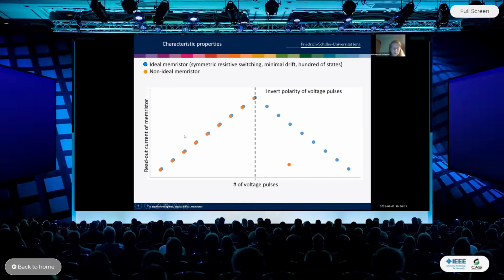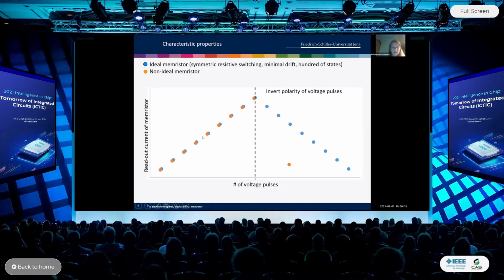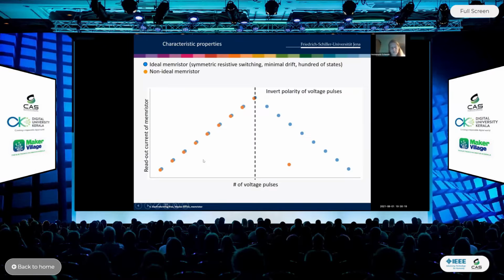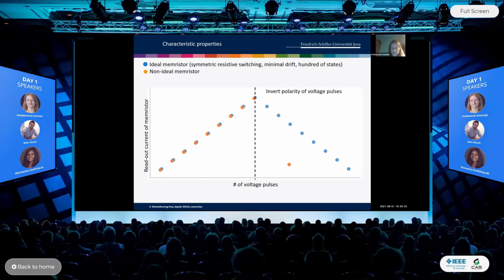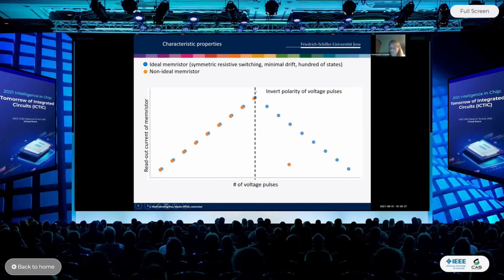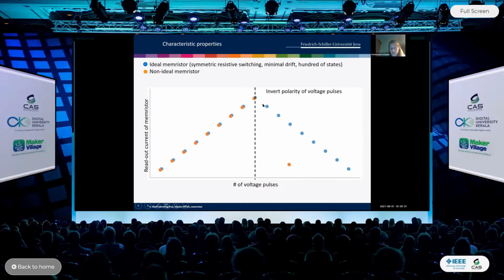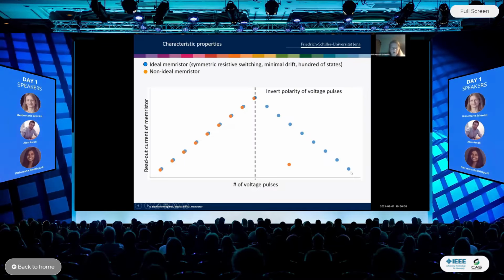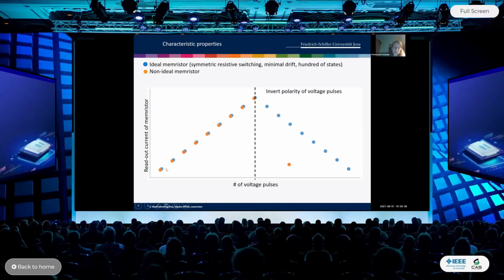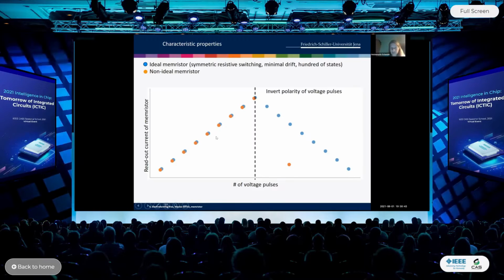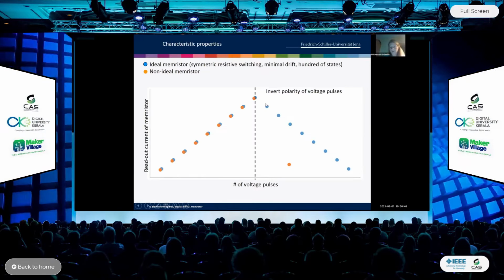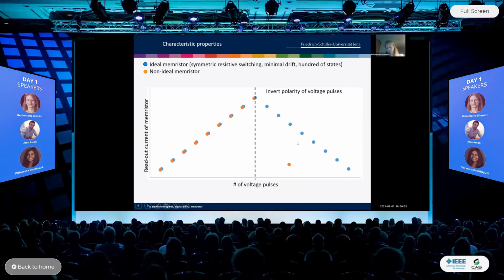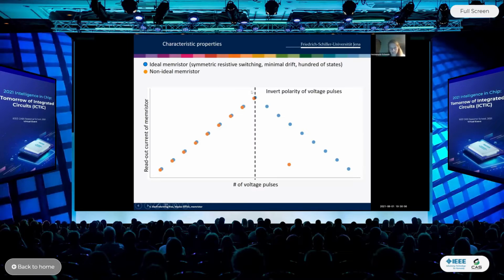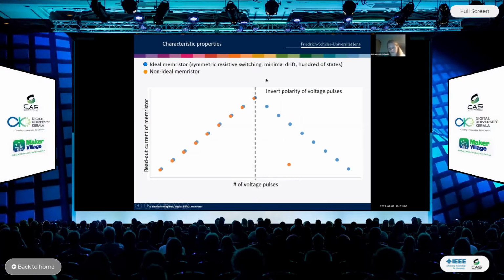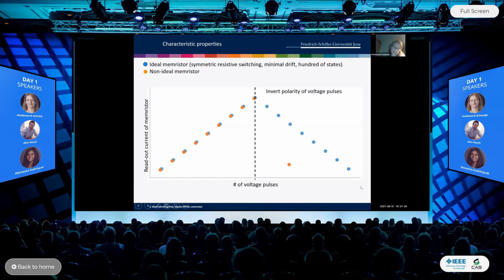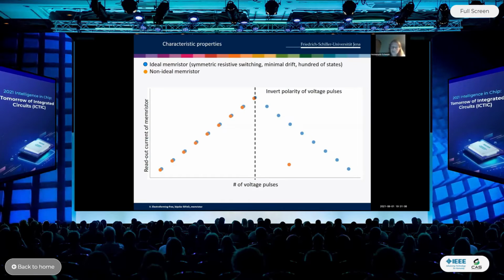And the ideal memristor should show a continuously changing readout current with continuously changing amplitude of the writing bias. And after the polarity of the writing bias has been inverted, it should be possible to bring the readout current successively back to the initial value. So far, there exist memristors which fulfill the condition in this polarity range of the writing bias. But as far as I know, only the bismuth iron oxide memristor, as I will show you in the following, is so far the only existing memristor which also shows, after the polarity of the writing bias has been inverted, the decrease of this readout current in dependence on the amplitude of the writing bias.